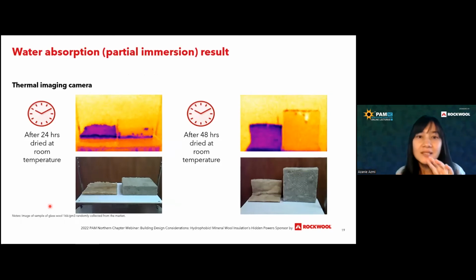So you can already see the difference here. For the thermal imaging camera, there's a slightly purple color. This purple color shows where the temperature is colder and where the material is highly soaked with water. What I did here is take the picture after 24-hour dry at room temperature as well as 48-hour dry at room temperature after the test. And you can see that for Stonewool, only the bottom has contact with water because we immersed it 10 mm, whereas the Glasswool is fully soaked. The purple color shows that the Glasswool is fully soaked.